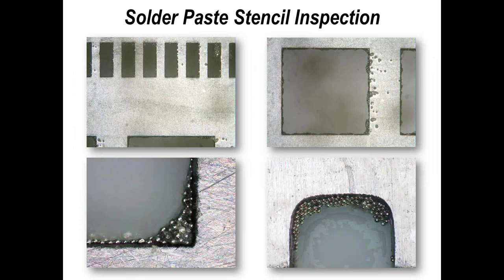or you can tend to monitor if you look at it close up. Now, again, we're all aware of the importance of cleaning stencils, and these are just a couple of examples of stencils that have been used but have not been cleaned. And if you have material trapped within the stencil and it's not cleaned effectively, or perhaps it's trapped in there after a few prints and you're not doing sufficient cleaning operations after the first print, then of course this is going to affect the volume, and also it's going to allow paste, perhaps not with a flux vehicle protecting it, so it reduces the amount of material on the surface of the pad.